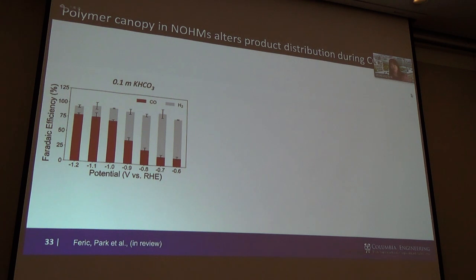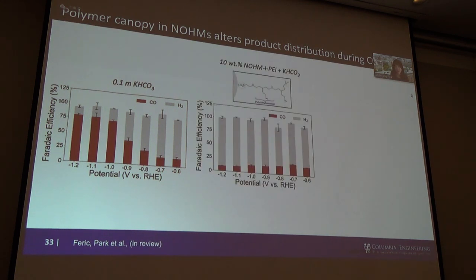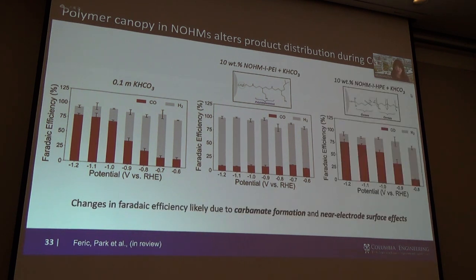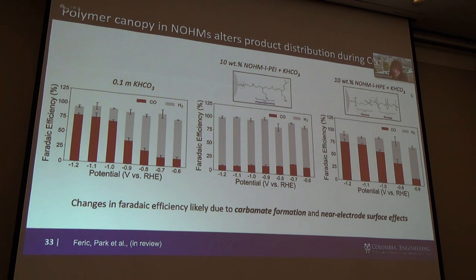This is a typical potassium bicarbonate electrochemical reduction of CO2. And as you can see, as a function of potential, you have different amounts of CO formation, and the hydrogen evolution reaction is suppressed at the increased potential. With the presence of NOHMs, 10 wt.%, it changed hugely how much CO is formed versus hydrogen. And if you look here, now with another system, the one in the middle with the carbamate formation, the last one is just having Lewis acid-base interaction between CO2 and NOHMs. You can definitely see the Faradaic efficiency change because the reaction pathway is changing significantly.